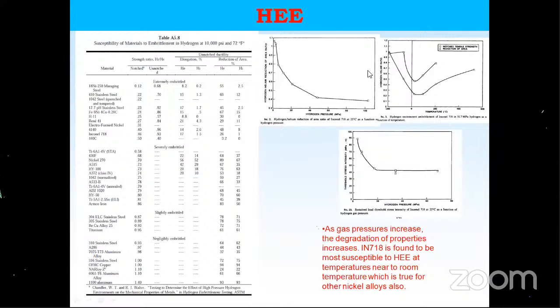Now, you will be asking why ISRO doesn't have an issue. ISRO doesn't have an issue because our hydrogen pressure is actually less than 10 MPa, that means nearly 100 bar. So we don't have much issue. We are somewhere here, whereas NASA they are somewhere here. So they have a real issue, but they manage with the help of coating and selecting special materials, which they have not disclosed.